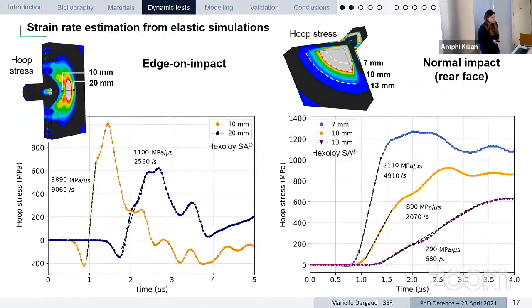In these two configurations, one idea is to quantify, or at least evaluate, the strain rate level reached in specific areas. So first, for the edge-on impact test, we use two points along the loading axis, and at these points we've plotted the hoop stress evolution with time. Here you see the plots, and from the slope of the tensile loading, we can get a numerical evaluation of the stress rate level in this material at these positions. For the normal impact, we did absolutely the same, but we've taken some points at the rear face of the ceramic at 7, 10, and 13 millimeters from the impact loading direction.